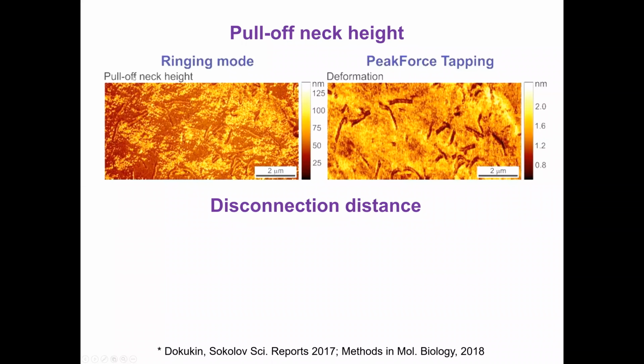So this is an example of maps of pull-off neck height on a cell surface. And this is recorded simultaneously with peak force tapping, showing the same surface of a cell. You can see there are patches, and you can even measure the size of these molecules. It literally gives it to you in nanometers. There are definitely patches on the membrane which have different viscoelastic properties.